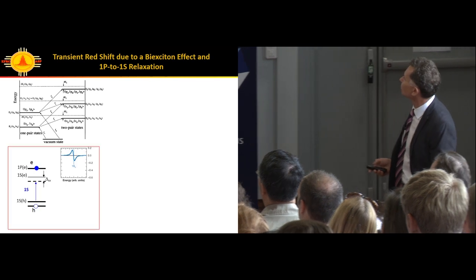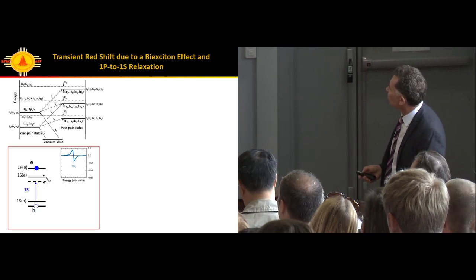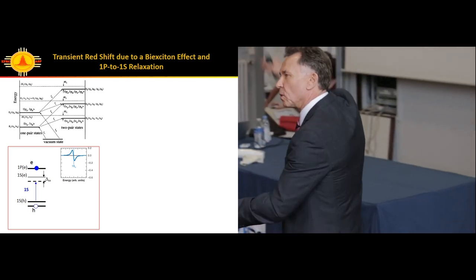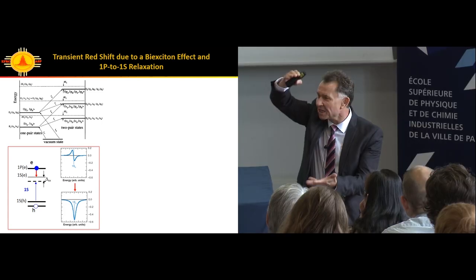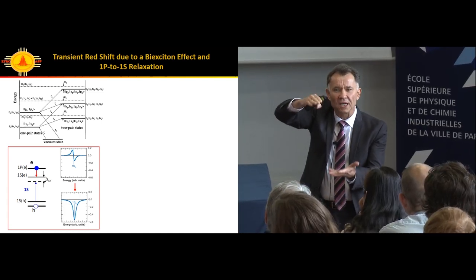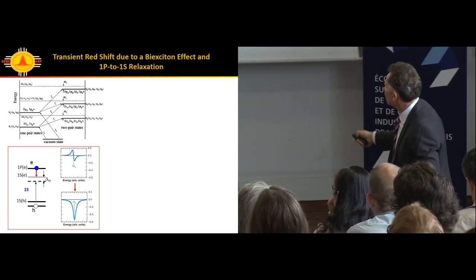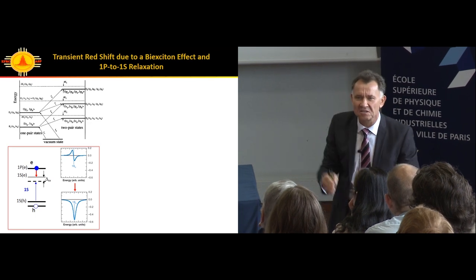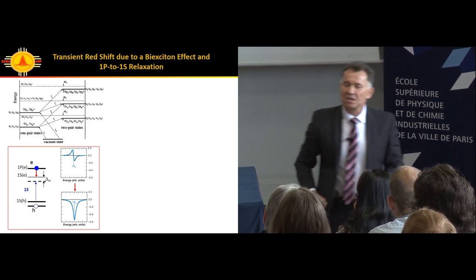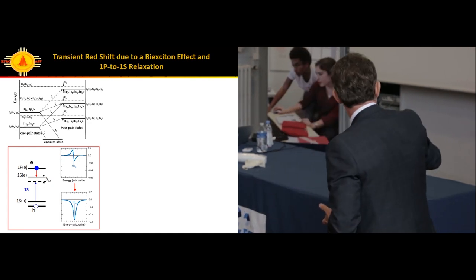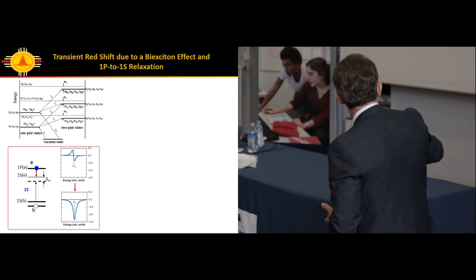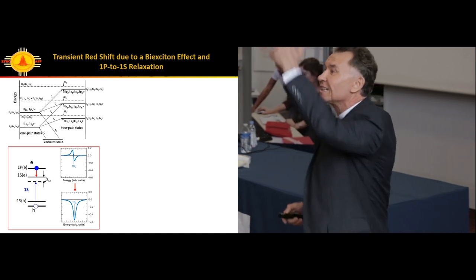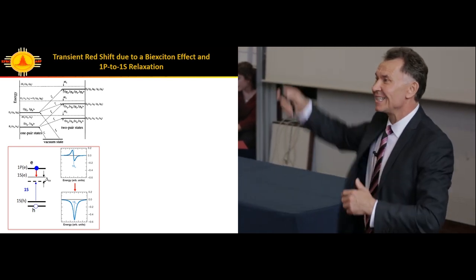This is the picture. We had the model in this particle-in-a-box. The carriers first excited in high energy states, second harmonic of CPM, 4 electron volts. That gives me a lot of time to look at unperturbed bandage. There are no carriers at the bandage. The lowest energy transitions are only affected by Coulombic effects. You make the exciton, you're trying to make the second exciton. The second exciton knows there's electric field inside the sample. It moves the transition, you create a new absorption at low energies, you remove the old absorption, you have bleach at higher energies. That explains this derivative-like feature.